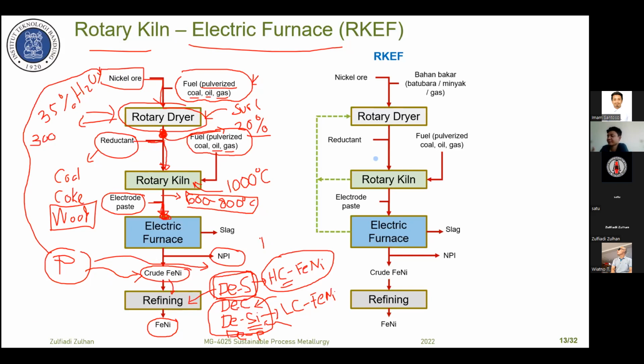in the product phosphor content usually should be less than 0.04 or 0.03%. That is a normal phosphor content in the product. If we have phosphor content, for example, more than 0.05%, I think in this case the buyer will give you a penalty, because phosphor is difficult to remove for stainless steel making. If they have charged the ferrochromium,